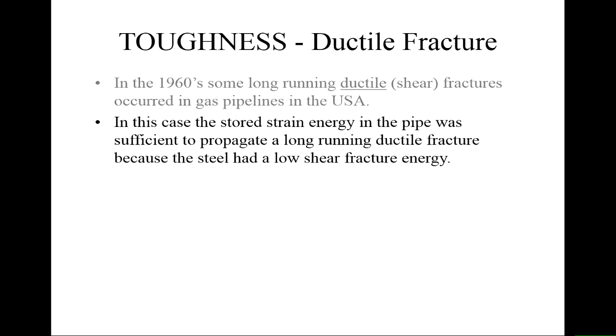So the stored strain energy in the pipe was sufficient because it had a low shear fracture energy, because the shelf in that ductile brittle transition was at a low level. And as I say, it's related to impurities, to sulfur and things that were in the steel.